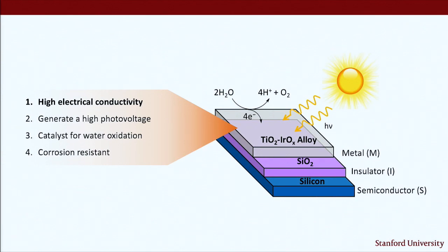And so as you can see in this figure, which shows the amount of iridium in the film as a function of the cycle ratio, I can very precisely control the amount of iridium that I want to incorporate into my film. And that's really one of the advantages of doing this by an all-ALD process, is the level of control that we get. Okay, so now I'm going to walk us through those 4 points that I talked about a couple slides ago and check them off as we go.